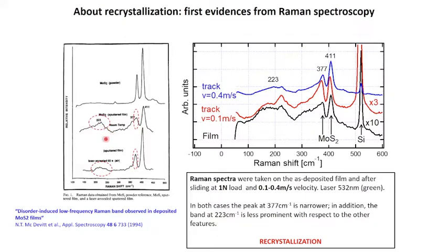After the annealing of the coating, which in principle increases the order of the film, the structure here at 377 gets sharper, so taller and sharper, and the features related to 223 decrease. So what we did, we took the Raman spectrum for the film as deposited, the black spectrum, and we compared it with the spectra collected on two different wear tracks. One is recorded considering a sliding velocity of 0.1 meter per second, and the other related to 0.4 meter per second. And it is clearly evident that the peak at 377 got taller and thinner with respect to the as deposited film.